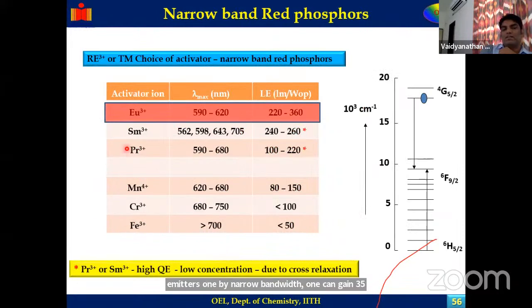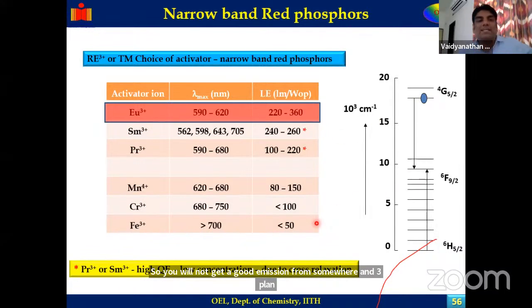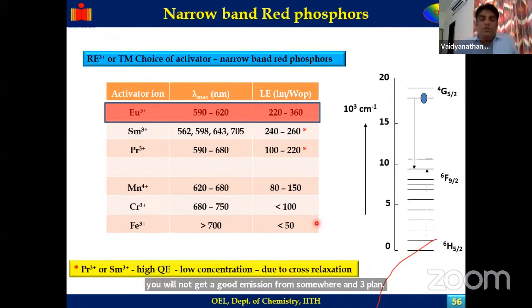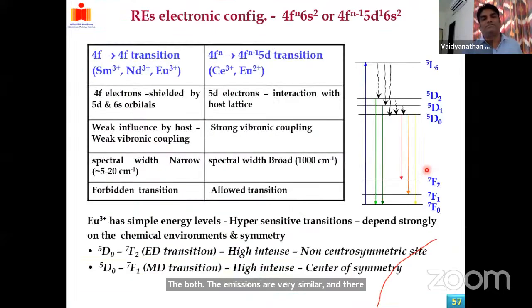Among all lanthanides, europium is better. Samarium 3+ also works to some extent, but due to concentration quenching, you will not get a good emission from samarium 3+. This is what is known as cross relaxation. When the photon goes from 6H5/2 to 6F9/2, the emission comes from 4G5/2 to 6H5/2 and 6F9/2. Both the emissions are very similar and there is a cross relaxation.